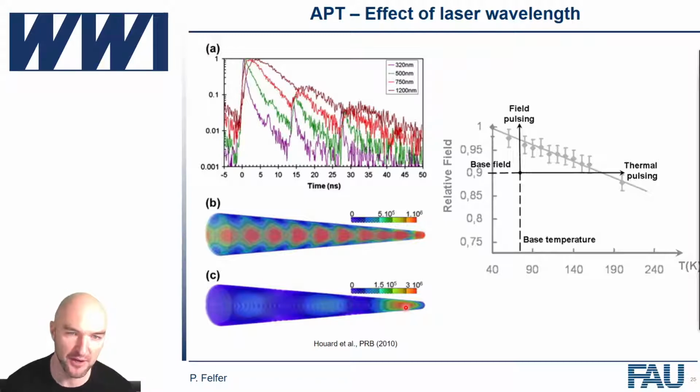And for infrared lasers, this is usually pretty well doable. But if you want shorter wavelengths, we usually have up conversion, and we lose a lot of power during those up conversion processes, so you're forced to focus a little bit more. Typically, I think the guys in Stuttgart use about 50 micron spot size. At 50 micron, vibrations and alignment don't matter as much.